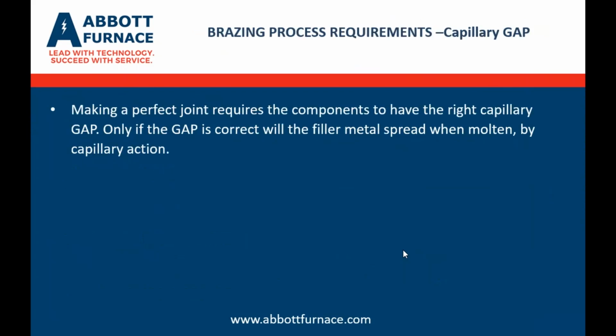As far as the capillary gap, making the perfect joint requires the components to have the right distance between the tube and the fins, or whatever the gap is. Only if that gap is correct can that filler metal spread when turned into a liquid phase via capillary action. A large gap reduces capillary action, and the smaller gaps restrict filler metal flow into the gap.